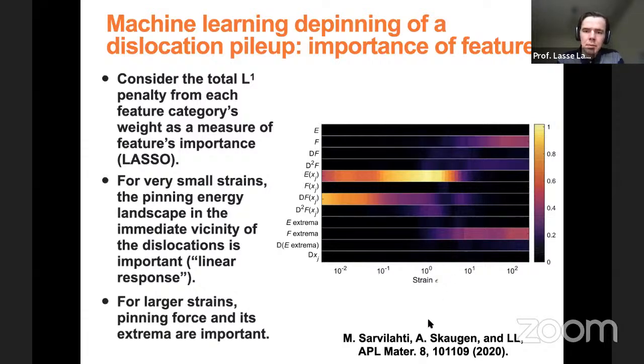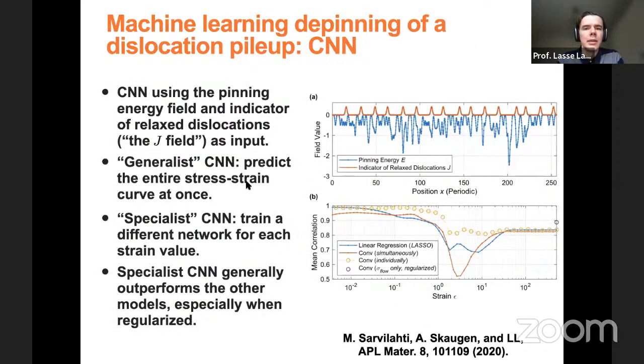Right. So yeah, then we can also do CNN, so convolutional neural network. And what we now feed as input for the CNN are the pinning energy field and some sort of an indicator of where the dislocations are in the initially relaxed state, which again we call the J field. So we have these two fields, which are now one-dimensional fields because this is a one-dimensional system. So you have some positions which are these peaks of this red curve of the dislocations initially, and then you have this pinning energy landscape here.